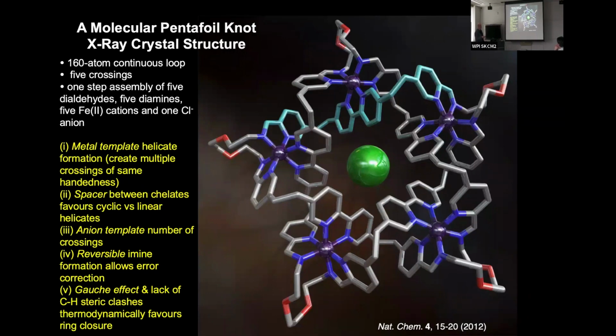So if you have chloride here, we get 5 crossings, and the reversible imine bond formation allows error correction. Even though we've got 5 crossings, if any one of them forms in the reaction that is a mistake, because these reactions are reversible, it'll all go through to the thermodynamic product, which is actually the knot.